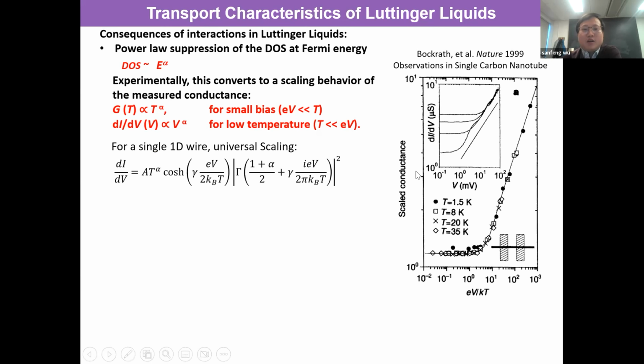So this type of measurement has been performed in previous one-dimensional systems, right? The single carbon nanotube or other systems. What's measured is the conductance as a function of both temperature and bias, and then you want to see whether they really collapse to a single curve in a scaled plot, so that you do have evidence of power law suppression of the density of states.